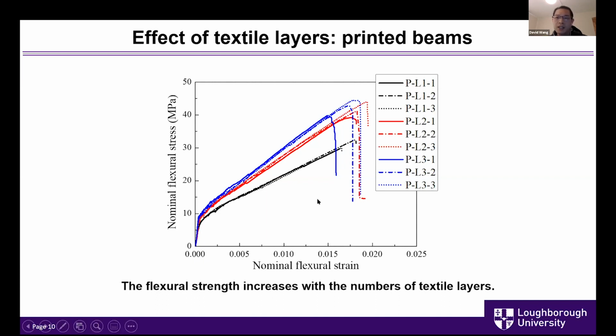Usually, the textile failed because of the tensile rupture of the bottom layer of the textile. So when the bottom layer textile is ruptured, the top layer, which is 5 millimeters above, has its tensile capacity not fully utilized.